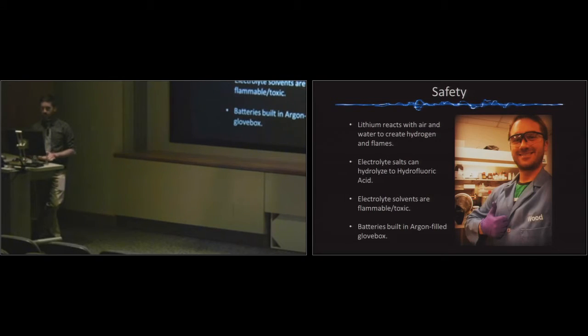So as an engineer, safety is always the first concern we have, so I'm going to talk briefly about that. I like to always bring that up and keep it at the forefront of everyone's mind. So lithium reacts with air and water. That can create hydrogen flames. The electrolytes we use have salts that can hydrolyze to hydrofluoric acid, which is pretty dangerous. And then the solvents in the electrolyte themselves are flammable and toxic. So what we do is we work with all these materials in an argon-filled glove box, which is pictured behind me there. And so this argon-filled glove box has no air or water in it, and that serves two purposes. It keeps the lithium safe from the air and water, and it keeps me safe from the lithium.